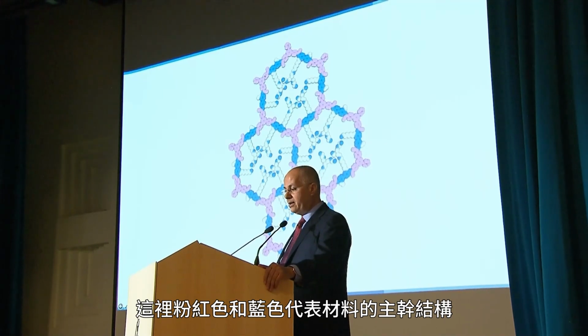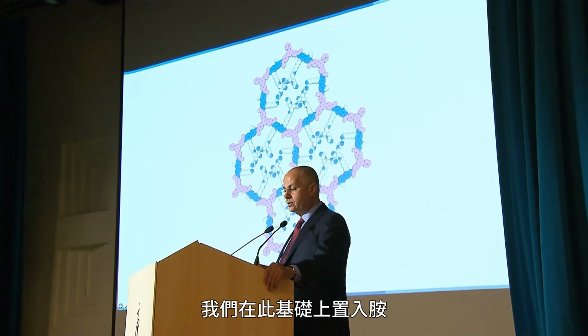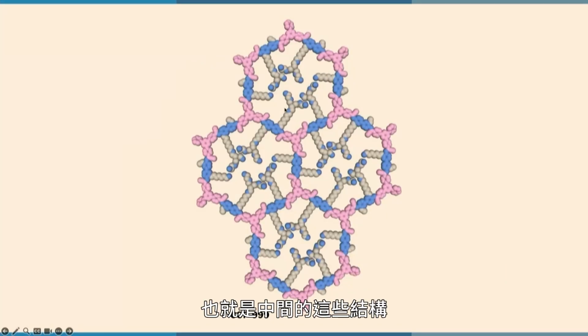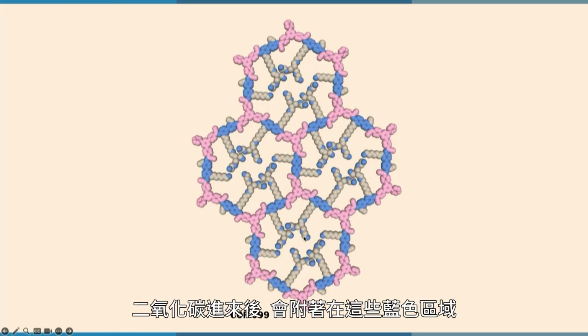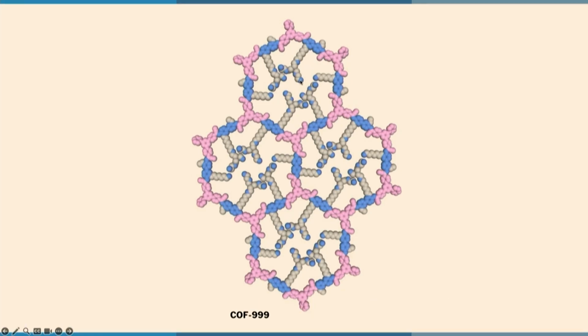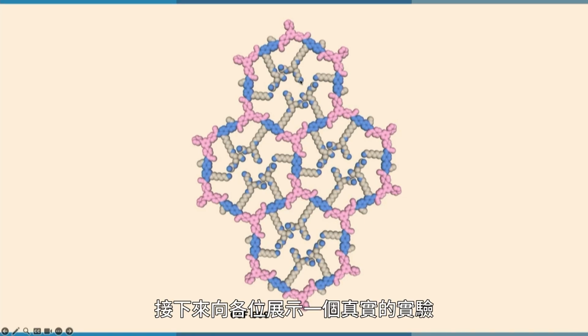And so here's the backbone of the material in pink and blue. And then we introduce amines. These are the things sticking into the center of the pores. And CO2 comes in and it attaches itself to these blue regions. These are the amine units. Okay, let me show you now a real life experiment.